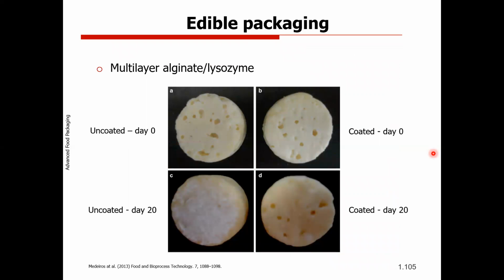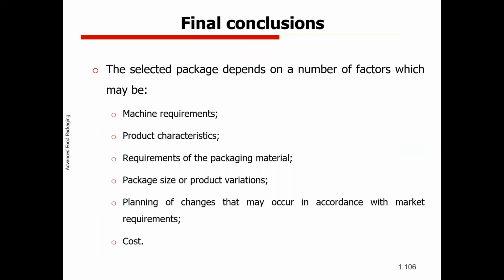Also to show you in cheese, we also did some tests with alginates and lysozyme, using uncoated at 0 days. You can see here uncoated. So in uncoated, you can see the growth of some fungus on the surface. We tested also other kinds of tests, and we checked that the multi-layer allows us to increase shelf life of these cheese products. So these are some of my final conclusions.